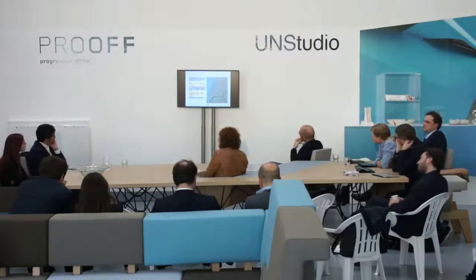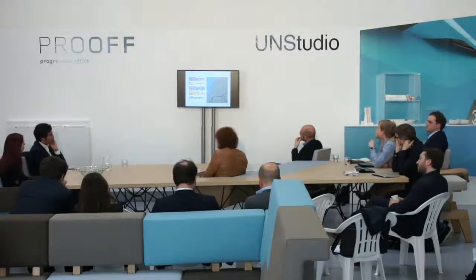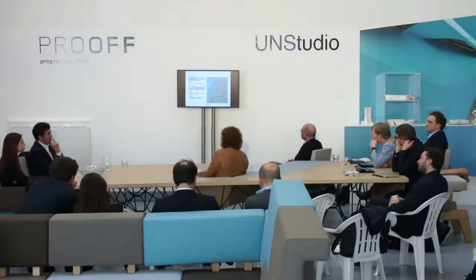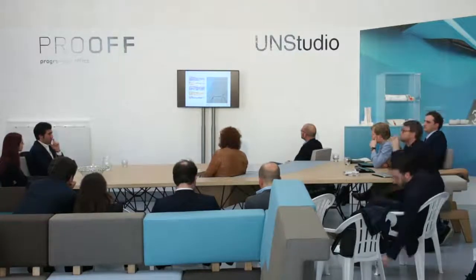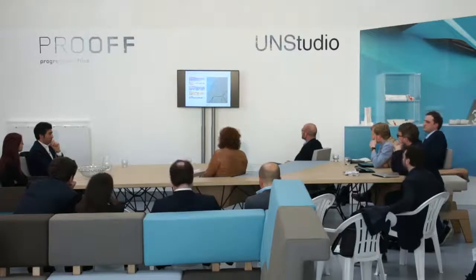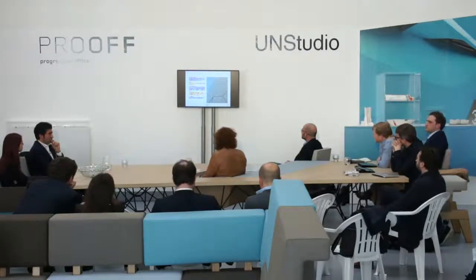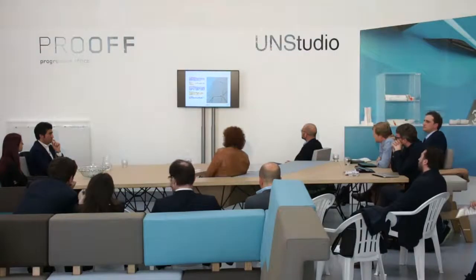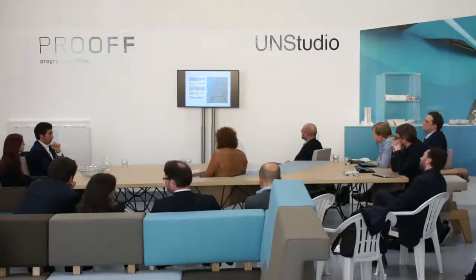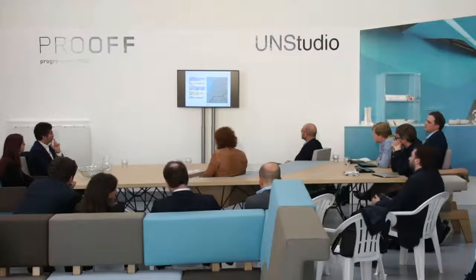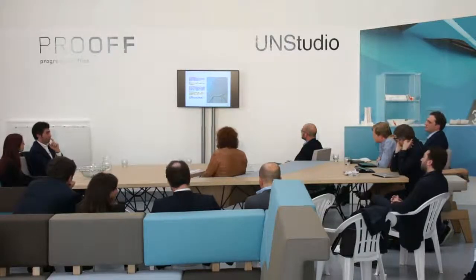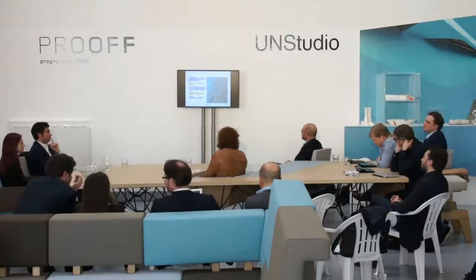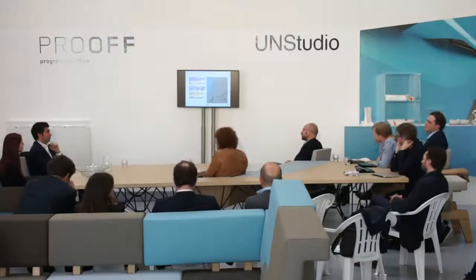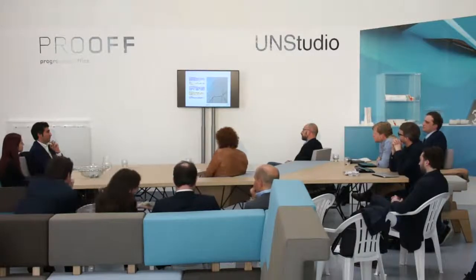I go there very quickly. Just a few values. If you use a normal 50 millimeter build-up composite panel, it has already a U value of 0.6. With additional insulation, usually rock wool or mineral wool, of 40 millimeters, you come down already to 0.35, which is very, very low. Still having a very light weight of this cladding. The weight, again, is very, very little. We reach around 20 to 30 kilos depending on the finish on the outside for structural composites.